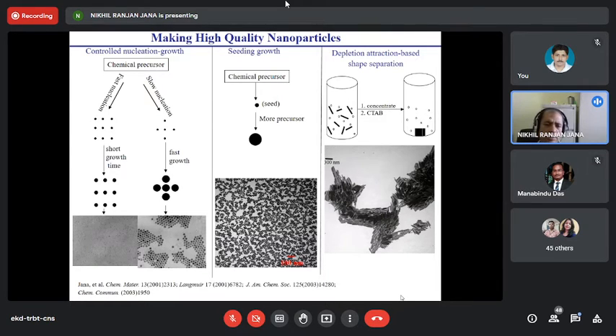If you want to make small particles, short growth time, nucleation and growth. Nucleate into small particles, then grow into larger size. If you use short growth time, you will end up with small particles. But if you grow for longer time with more additional precursors, you will end up with large particles. Fast nucleation and short growth time is ideal to make small particles. Slow nucleation and fast growth: only a few nucleation centers in a solution. You start with a metal solution, only a few nucleation sites, and grow on those sites for a long time, you will end up with large particles.